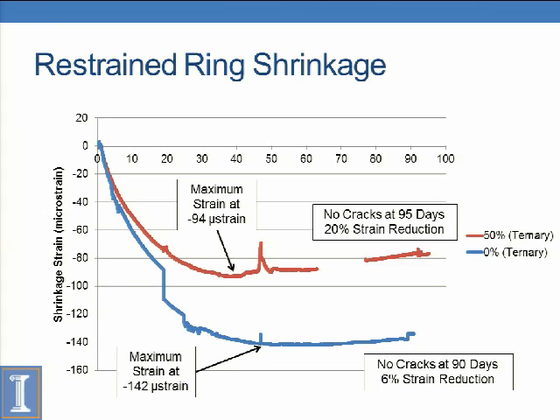You see a bump here. A bump usually means a crack. In this case, there was a malfunction in the shrinkage room, and the temperature went down and resulted in a few of our data having spikes like this, but there was no cracking, pretty much just a spike due to that. And you can see if we ignore that spike, the strains went on at the same rate. So pretty much after 90 days or so, we stopped the test after no cracking. We could see that the 50% mix had lower strains than the 0.